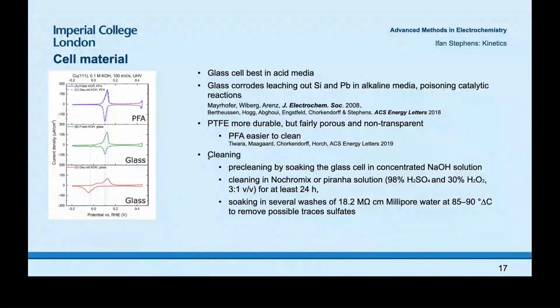Of course, apart from the materials that electrodes are made of, it's also important to consider what cell material you're using. Anthony already alluded to this. Generally, in acid media, I'd only use a glass cell. However, in alkaline media, glass cells often corrode. You leach out species such as silicon and lead, and this can poison catalytic reactions. In my own group, we found poisoning, for example, in CO reduction in alkaline media. The copper becomes much less active with time, essentially because we're building up silicon oxide at the surface. And others have found similar results on platinum-based catalysts in alkaline media as well.